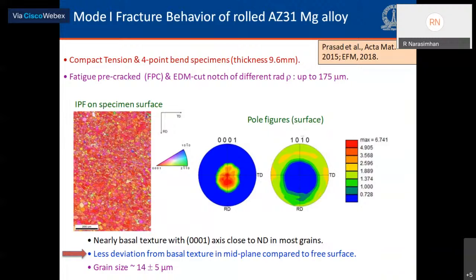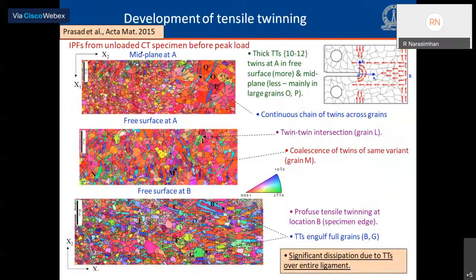We can make that out clearly if you look at the 0001 pole figure on the right side. The intensity, the red region, is not exactly at the center, which is the ND, but a little offset towards RD. This deviation we found is less in the midplane of the specimen as compared to the free surface, and we believe that this is attributed to the rolling operation. The average grain size for this alloy is around 14 microns.